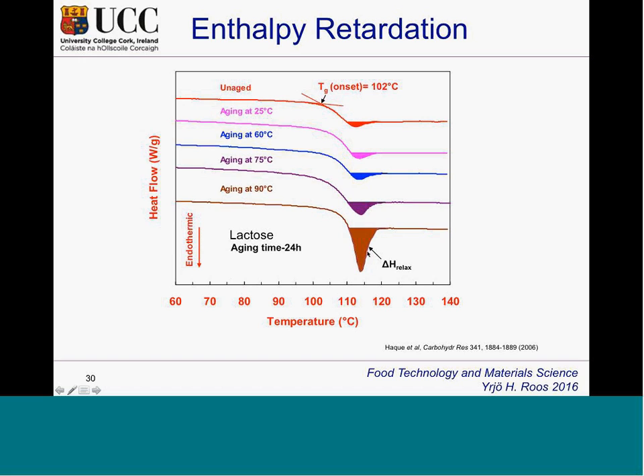return of enthalpy is quite much. Sorry, it is not below. The glass transition is about 100, so this is very close to the glass transition. This is far away from the glass transition. This means that it's very hard. It doesn't happen much in 24 hours. But close to the glass transition, you see quite a lot of changes.